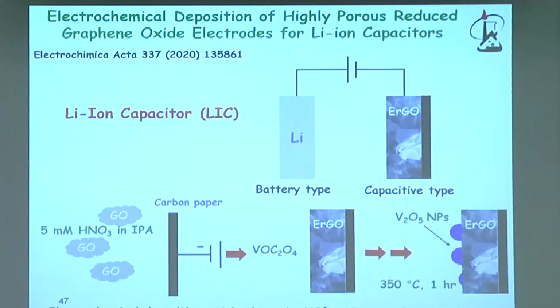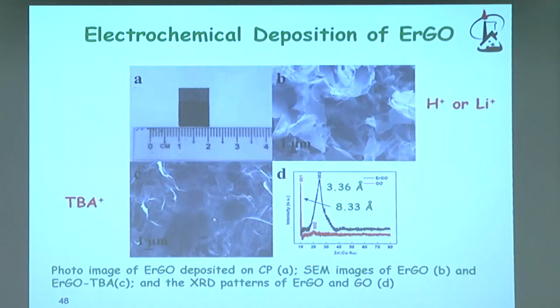And we did one example. I'll go very quickly by that. So we are working on lithium-ion capacitors, and basically we are working on supercapacitors. And again, the challenge is to increase the specific energy of the capacitor. And by that, what we were doing is we were depositing the graphene oxide by reducing it, and then added a type of vanadium oxide inside as a battery type material, and by that we can increase very much the specific energy. A big advantage of this electrochemical deposition in this case is that we want to actually generate also hydrogen in order to make the reduced graphene oxide very porous and with very high surface area.